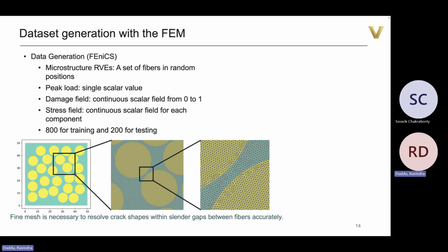And so let's say we generated 1,000 of those, then we have to mesh them. And because the phase field length scale is so small, and we want to capture fractures that go between fibers in these very tiny narrow gaps, imagine how much we have to refine. So this is a 50 micron by 50 micron domain. You take a small chunk of it, and then you zoom in. You still cannot see the mesh very well. Then you have to zoom again, and then you're seeing the triangular mesh, right?